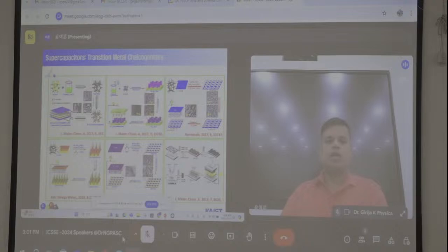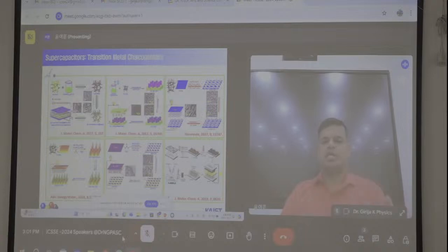That material has some issues, therefore we moved to grow the active material over the nickel foam. You can see we fabricated materials like oxide, then moved to sulfide and then selenide. Why move from sulfide to selenide? Because compared to sulfide, selenide has high porosity, because the selenide size is very large. Then the porosity is enhanced. Therefore, electroactive sites increased, and finally energy density and power density also increased.